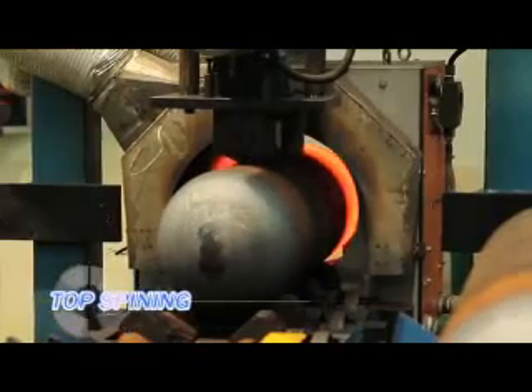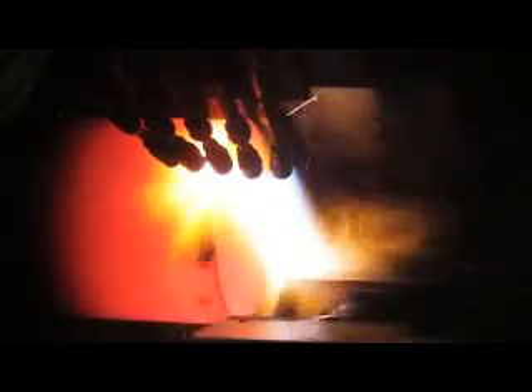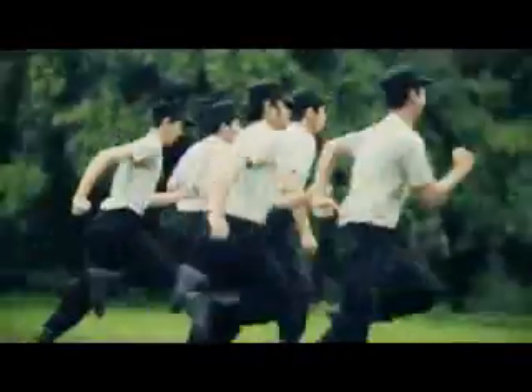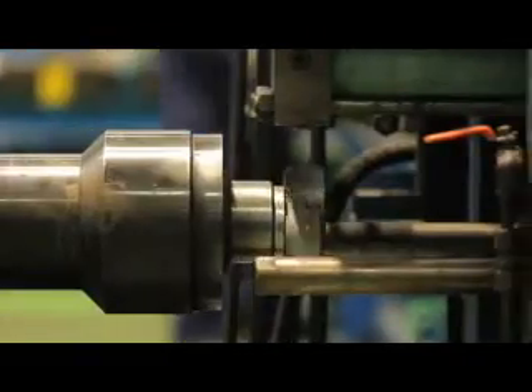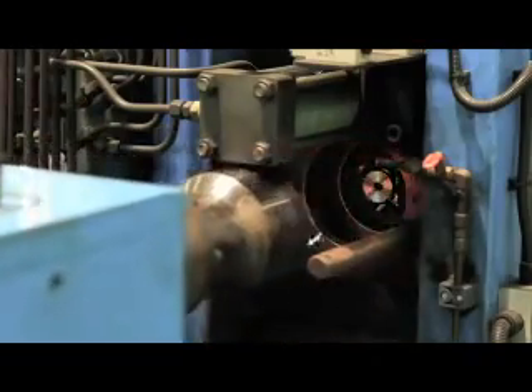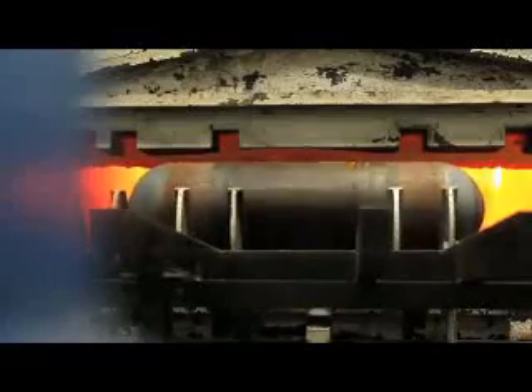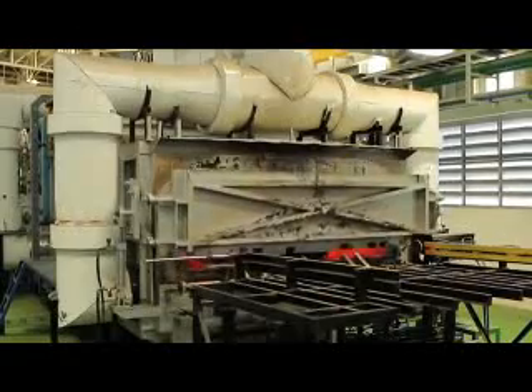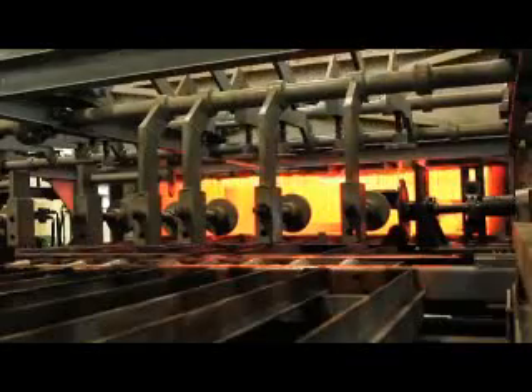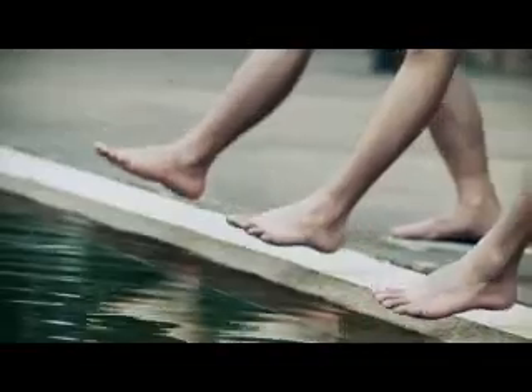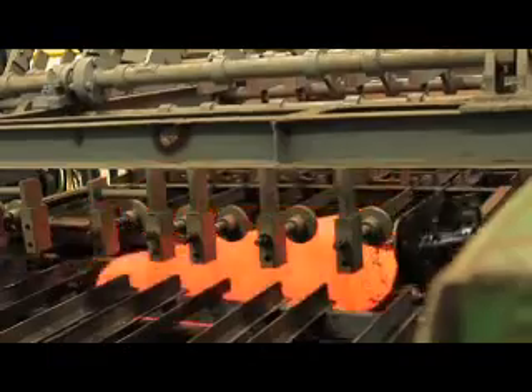Top spinning: induction preheating of the cut pipe's top at 1200 degrees Celsius before hot spinning and then hot top neck spinning. Neck cutting: cut the neck and drill a hole. Heat treatment is to adjust the qualification of the tank. This process consists of three steps. One, hardening process to adjust the hardness by heating at a temperature of 870 degrees Celsius for 50 minutes.